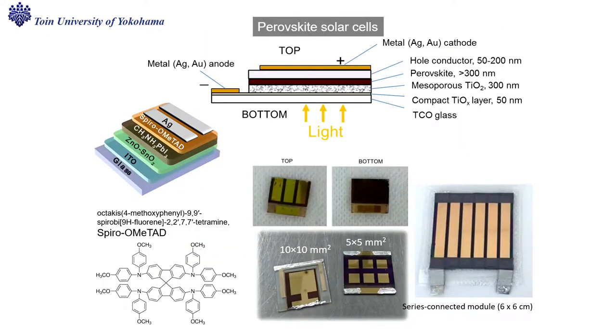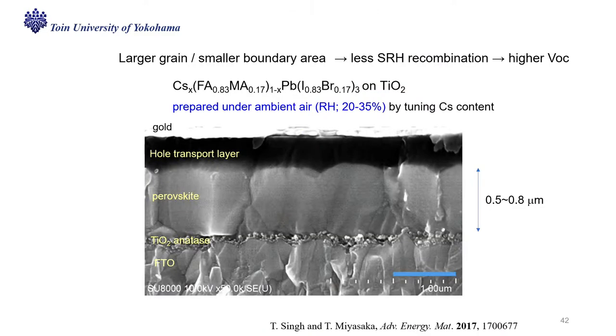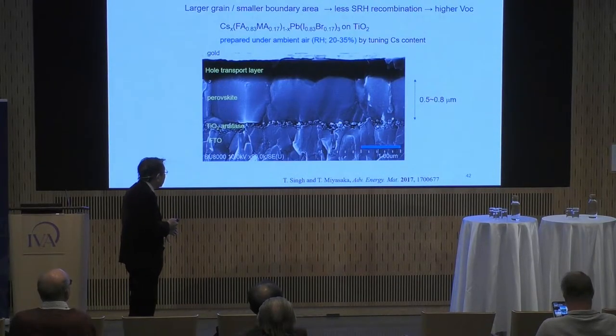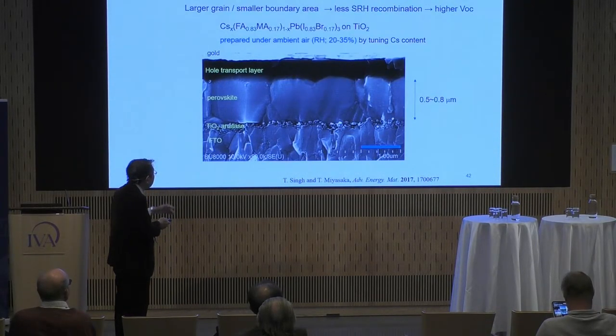This is the outer structure of the perovskite sandwich cell. And we need to use the hole selective layer and electron selective layer to enable efficient charge separation to get the photocurrent density. So this is a section view. Perovskite is very, very thin, 0.5 to maybe 1 micron thick. So with this thickness, all incident light is absorbed. Because it is very, very thin, we can make a thin film device on plastic. It's bendable, and no cracks are produced because of the very, very thin film.